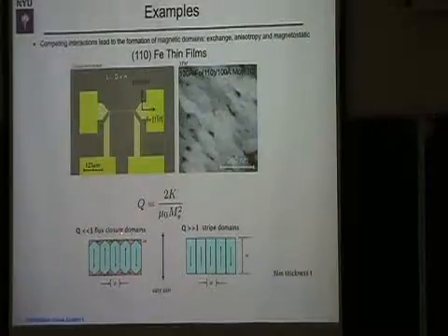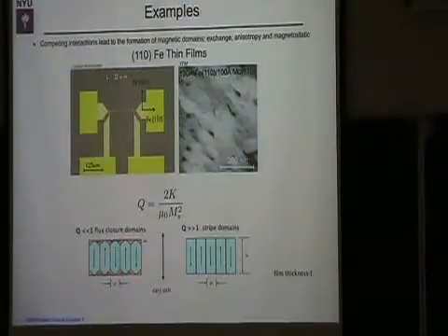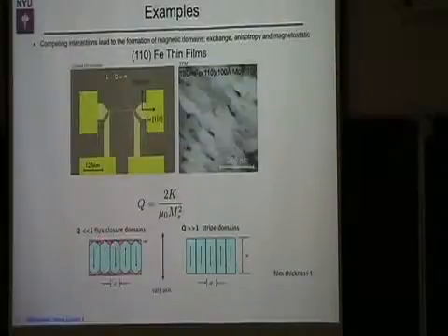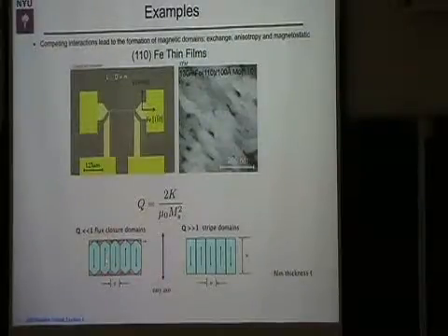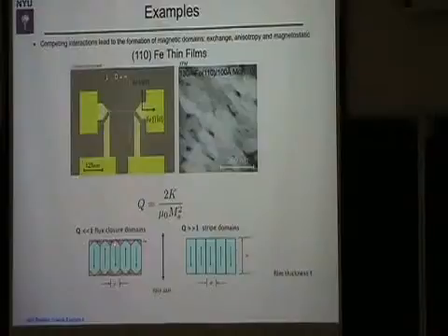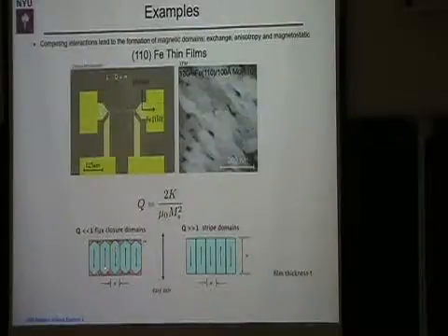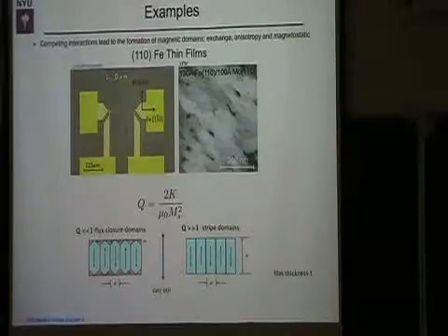If it were uniform, you'd have a discontinuity in the magnetization, and you'd have large magnetic fields outside the sample. So a lower energy state is to form what are called stripe domains, where the magnetization alternates between up and down to reduce the magnetic field. It can reduce the field in two ways. It can form little edge domains, so that if these lines are at 45 degrees to the magnetization, then the normal component of magnetization is continuous, and you minimize the magnetic field, with a closure situation where the magnetic flux is closed. Or if the anisotropy is very large, larger than the demagnetization field, the system can form stripes without these closure patterns.